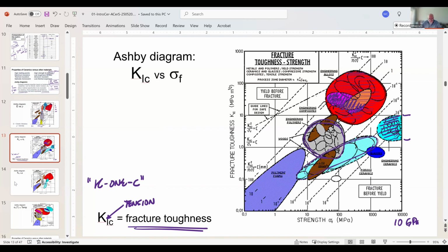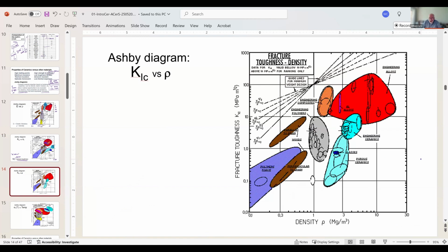Okay. So if I come down to the next one and look at fracture toughness versus density, density here we designate with a rho. Now your ceramics are low density, which is good for us. This is porous ceramics here, and here's my engineered ceramics. My fracture toughness values are as before, but at a lower density range. So what do I give up when I go to engineering alloys? Well, I might be able to keep the same density range in my aluminum alloys and some of my titanium alloys, similar to ceramics, but I get much better fracture toughness.